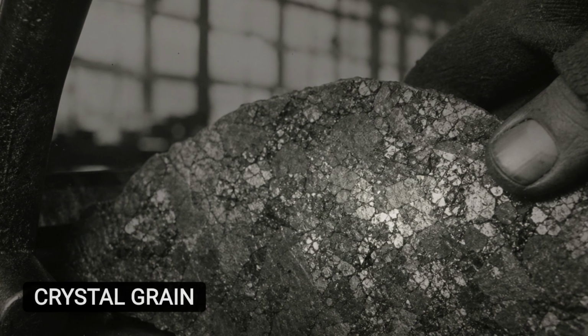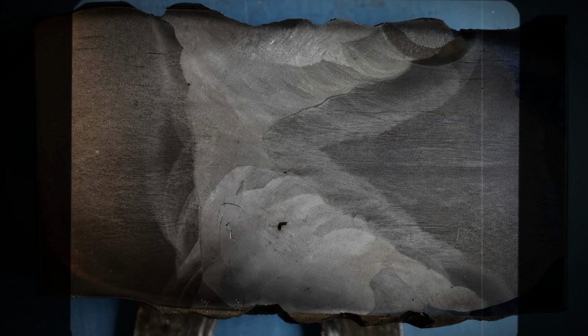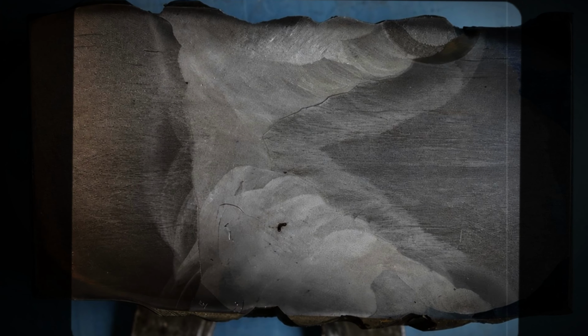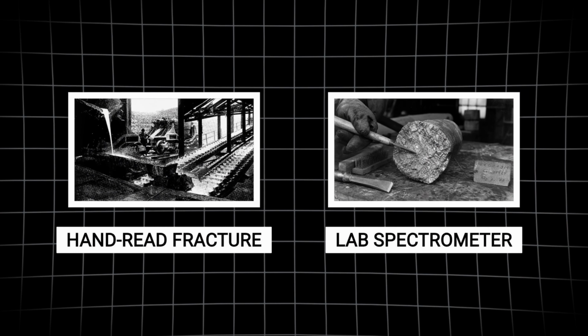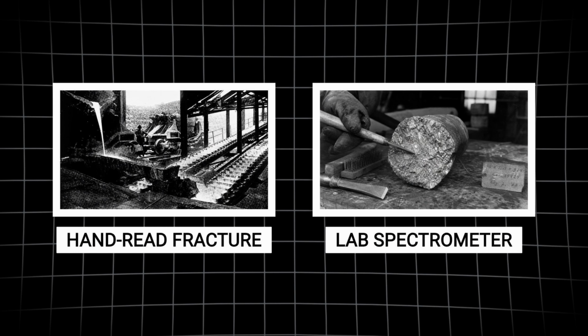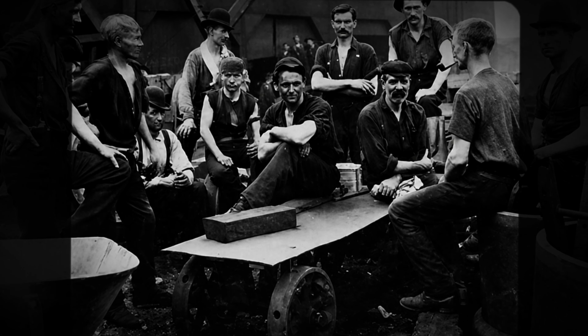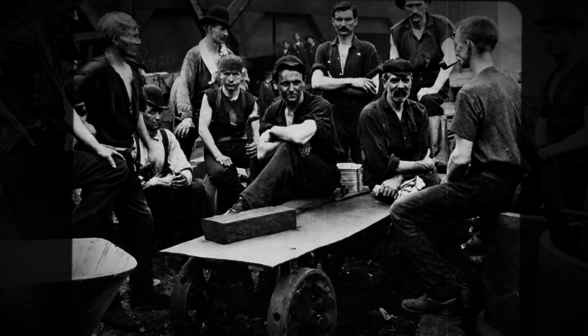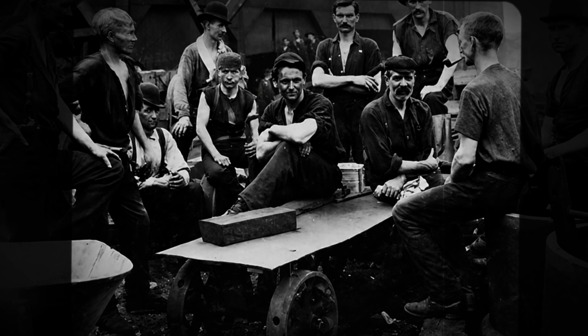The size and shine of the crystal grains told him the carbon content, not roughly, but to within a few hundredths of a percent. A fine, silky fracture meant one grade, a bright, coarse sparkle another. He could see overheating in the grain. He could see brittleness. In the days before chemistry labs, entire mills shipped steel graded almost entirely by fracture, and railroads bet human lives on those readings, and the readings held.